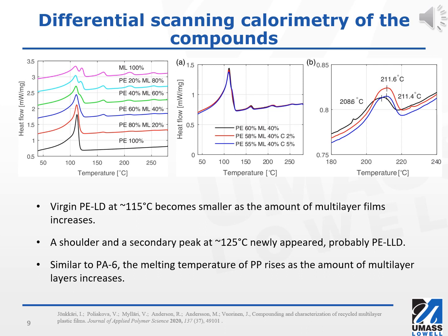As the number of multilayer films increases, the amount of virgin LDPE that can withstand 115 degrees Celsius decreases, and a shoulder and a secondary peak at 125 degrees Celsius have emerged, most likely LLDPE, which is linear low density polyethylene, in a manner analogous to that of polyamide. The amount of multilayer layers contributed to an increase in the melting temperature of polypropylene.